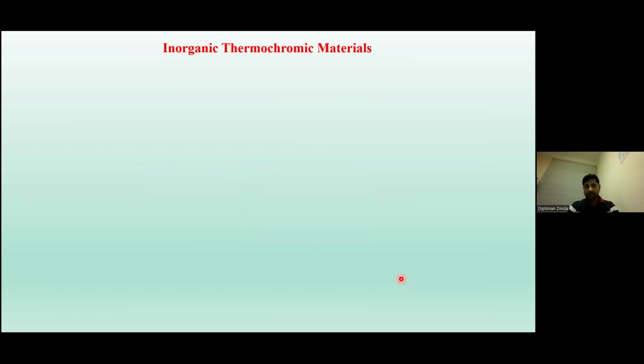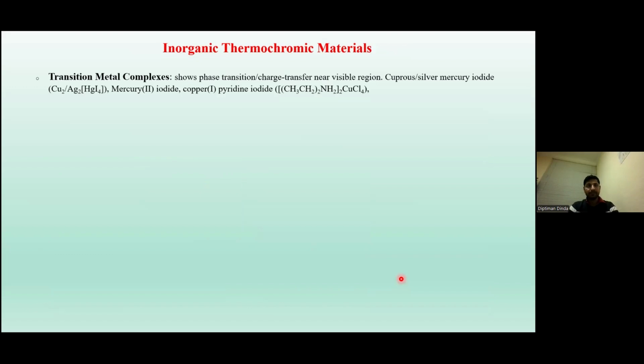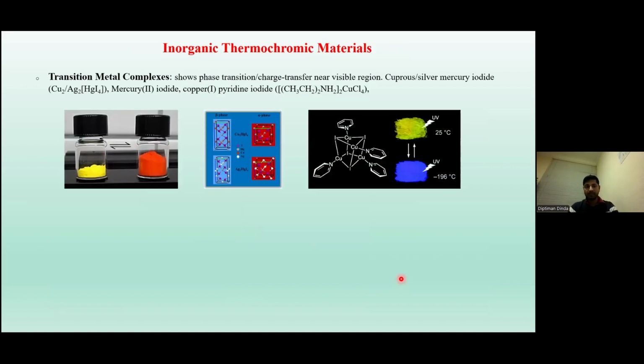So apart from organic, inorganic materials can also be explored for this purpose. There are many transition metal complexes like mercury iodide or copper silver mercury iodide. They mainly change their phases from alpha to beta phase with applying heat, and they change their color. Or if we can make different charge transfer complexes such as pyridine iodine complexes with coppers, then because of this charge transfer effect, they will change their absorption and eventually the color.